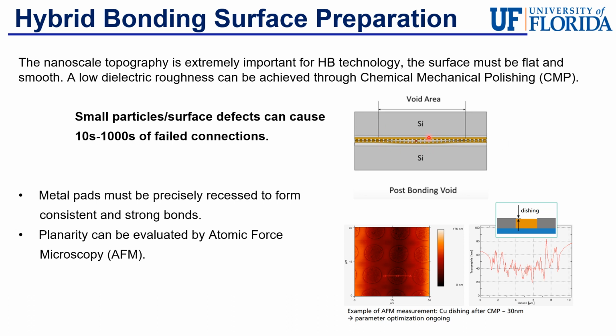A single particle or defect could cause this large void area to form between the wafers, which would disrupt the bonding process between the metal pads, ultimately ruining the whole process because none of the connections would function properly. And the smoothness, or the low dielectric roughness, can be achieved through a process called chemical mechanical polishing, which is typically a proprietary process that's unique for each manufacturer because they all have their own slurry recipes and polishing parameters that they use.